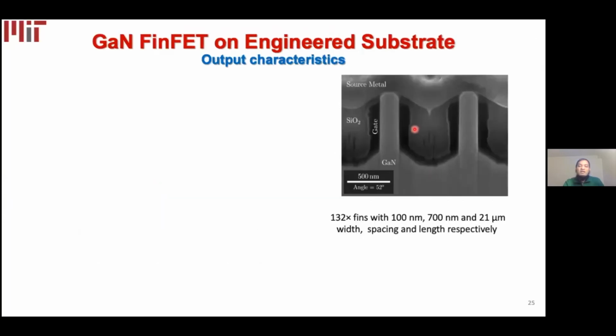And this is a cross-section focused ion beam image of one of our typical fabricated devices, where we have the gallium nitride patterned fins, the gate metal on the side walls, the silicon dioxide spacer, and the source metal on top. So this is the spacer layer, which is separating the gate and source metal and avoids them being shorted.